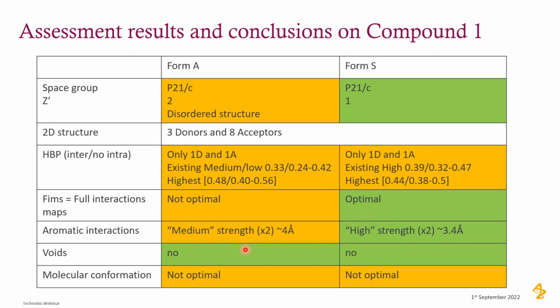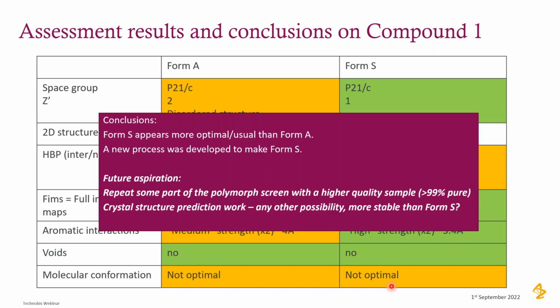You've got another tool from the CCDC Mercury software, which is called aromatic interaction, and it does show basically that Form S has a high interaction in terms of aromatics compared to Form A. There are no voids, and the molecular conformation is basically non-optimal in both. So when you look at that picture, you realize Form S seems to be more usual than Form A, but the risk of another form which could have a stronger or better propensity for hydrogen bond may still exist.